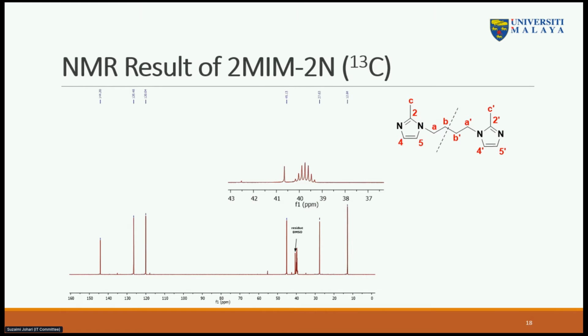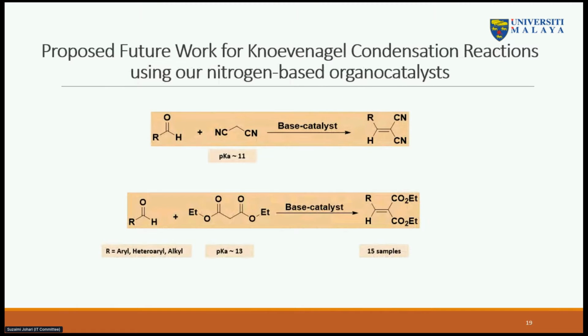This also indicates the results from the carbon NMR of catalyst 2, and you can see that there is still a little solvent found in the NMR. However, we are now trying to crystallize it, or at least reduce the amount of solvent. The rest of the peaks seem to match the compound well. And as I mentioned before, this work is still preliminary, but we have already completed the characterization and synthesis of catalysts 1 and 2, and we hope to get better characterization results, especially for the purity of catalyst 2.